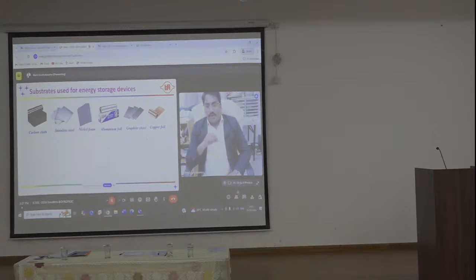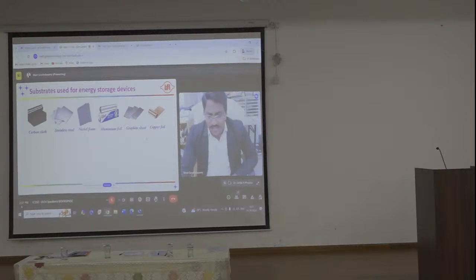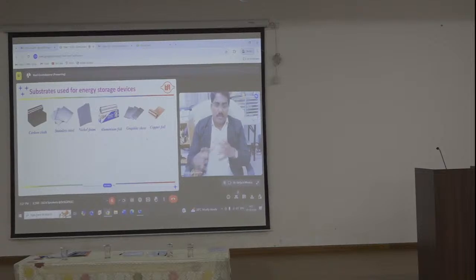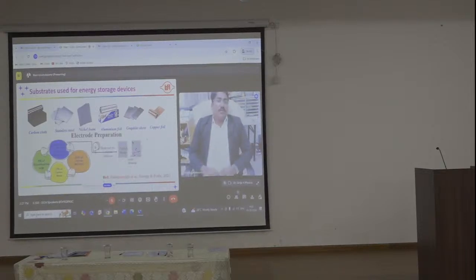Mostly in my research lab, we are using carbon cloth as a flexible substrate and nickel foam. These are the substrate we are using, and stainless steel also. Not stainless steel, I mean stainless steel mesh, so it's a very flexible material, similar to the nickel foam. So these are the substrates we are developing. For example, it's a very simple procedure. So in my lab we are using different kinds of fabrication. Very similar procedure, we are using some binders. Sometimes we develop in-situ material preparation on the substrate, but mostly we use the coating technique to prepare the nickel foam with different ratios of the carbon materials and active materials, and then even binders we are using to make the electrodes.